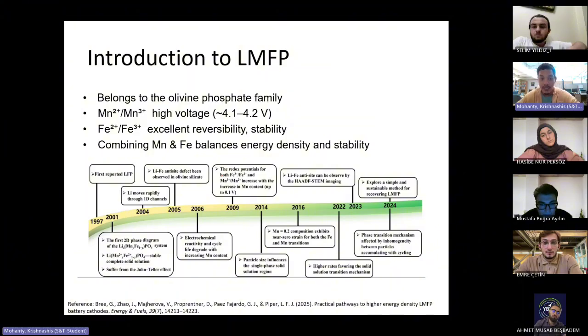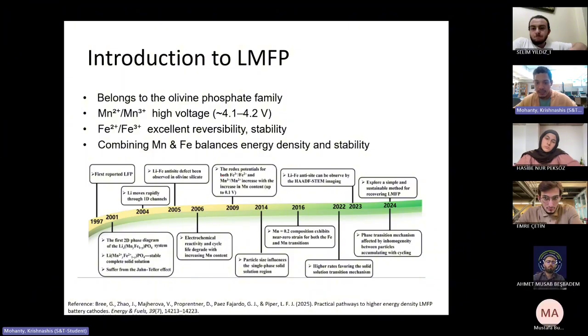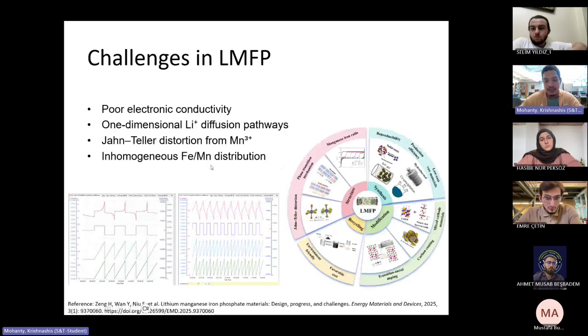And again, just adding manganese to the structure itself does not solve all the problems. Iron is stable itself. Manganese has energy density, but it does not have stability. So we have LMP cells, which are lithium manganese phosphate cells, but they are not used extensively, even though they have high energy capability as compared to LFP, because they're not stable. They give in to thermal runaways, SEI growth, and stuff like that, because it's not stable. And I'll go into why they're not stable. So that's just an overview of LMFP.